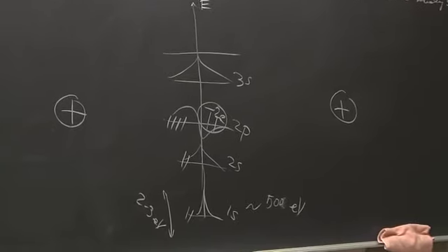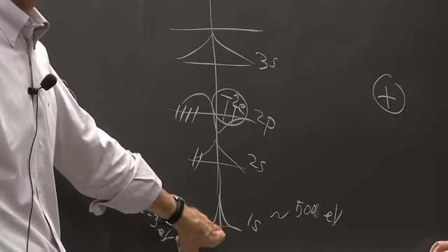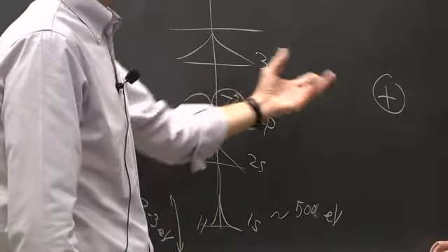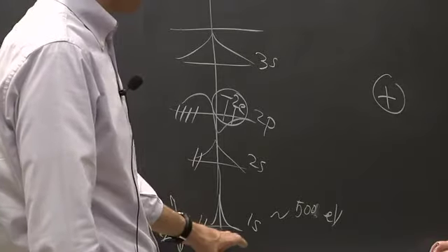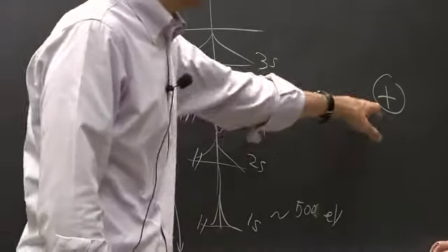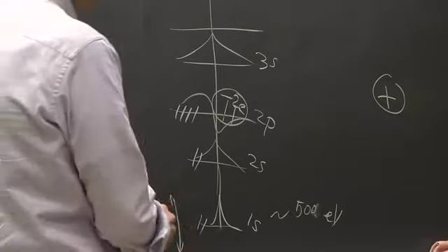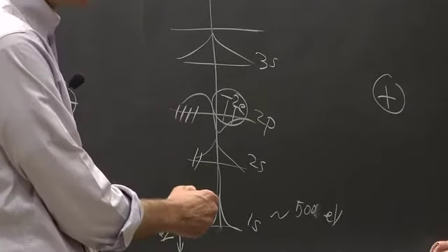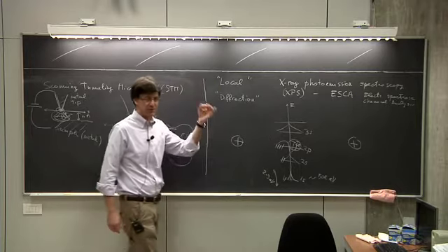So this state will go up and down just because the electrostatic potential at this point is changed by the fact that you have charge transfer, or because you have some positive charge outside. So the position of the electrostatic potential is very sensitive to the charge state of your atom, but also to the position and charge state of your neighbors. At this point, you can think of doing experiments in which, with a photon, you take this electron out and you bring it to outside your sample.